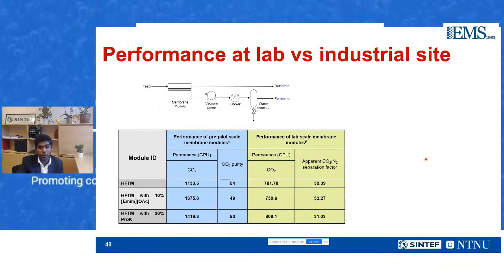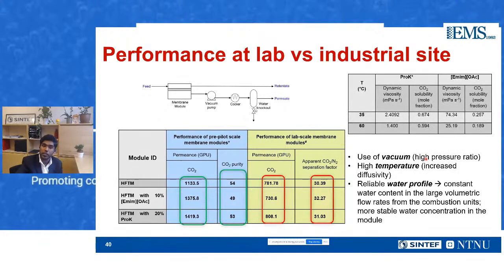So the performance, on the other hand, what we obtained at industrial scale was much better with respect to the lab scale. When you look at the permeances, it was quite high. The CO2 purity was also about in the range of 50%. The reason why we get this very high performance or increased performance with respect to the lab scale performance of these modules is because we use vacuum on the permeate side because of the good area, high membrane surface area. So use of vacuum is justified, which increases also the pressure ratio, and high temperature of the flue gas, which was around like 80 degrees to 90 degrees. And also because the water profile in these systems are much more predictable and reliant. And that's the reason why we were able to record very good performances in the field than in the lab scale.